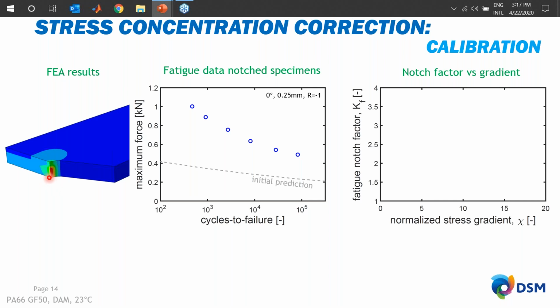And you can see also here that the stresses at the edges are higher because of the shell-core type of structure. But it gives a problem, because if you use that local extremely high stress to also compute your lifetime, then you will always underestimate the lifetime of your part. And that is illustrated here in the middle. So here on the y-axis you have maximum force plotted versus the number of cycles to failure. And you can see the markers here are measurements, and the dashed line is, let's say, the initial prediction when you just use these local high maximum stresses. So it's not very good actually.